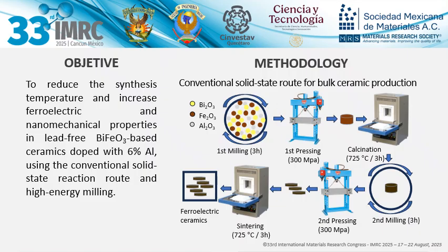Methodology. The synthesis was carried out via the conventional solid-state reaction route. Two samples were prepared, one of pure bismuth ferrite and another doped with 6% aluminum at the B-site of the perovskite structure ABO3. Commercial high-purity precursors, bismuth oxide, iron oxide, and aluminum oxide, were used. The mixture was milled for 3 hours, uniaxially pressed at 300 megapascals, and then calcined at 725 degrees Celsius for 3 hours. Subsequently, a second milling, pressing, and sintering were performed under the same temperature conditions.